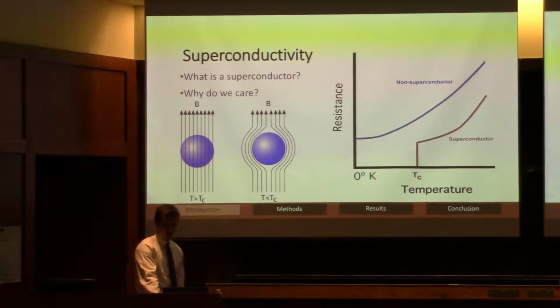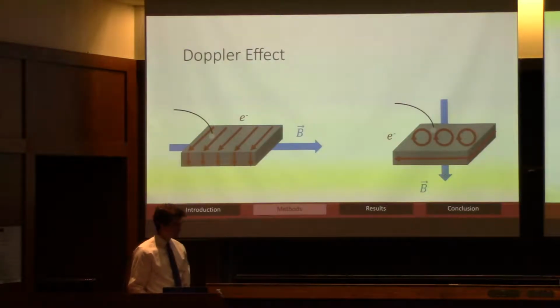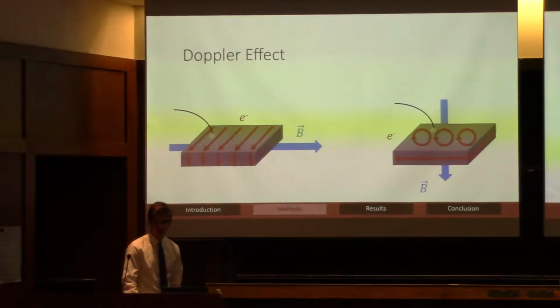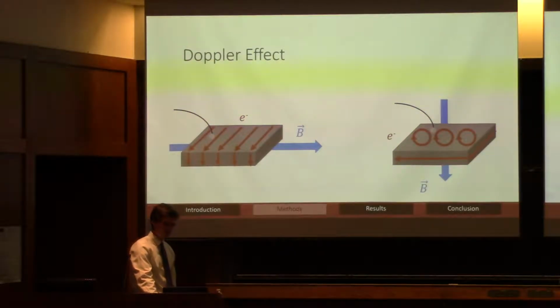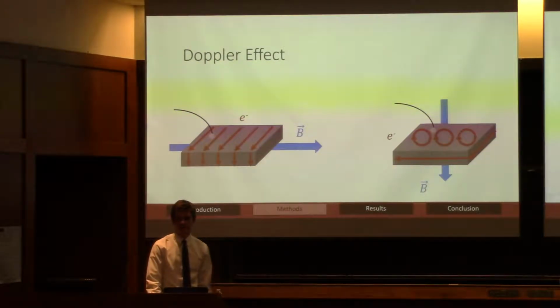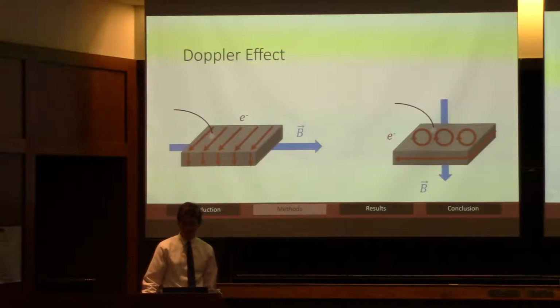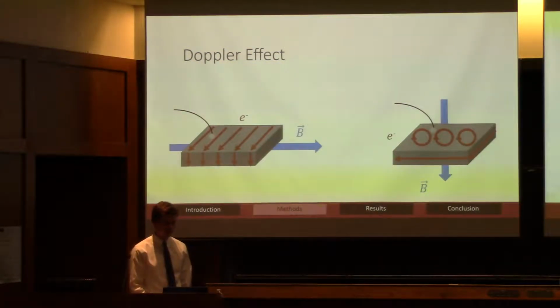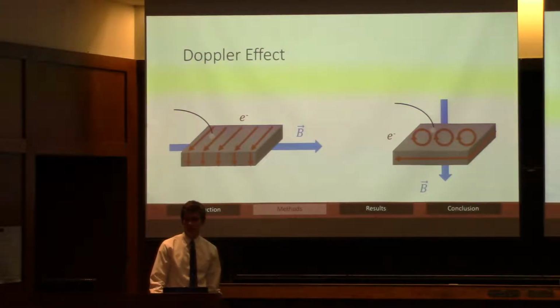Now this Meissner effect leads to something called the Doppler effect. And these are those currents that I was talking about that get induced by that magnetic field. So these are two different orientations of a superconductor in a magnetic field. On the left, you have the face of that sample parallel with the direction of the magnetic field. And these red arrows are the direction of that superconducting condensate that's moving around that sample to cancel out that magnetic field. So as you increase the strength of this magnetic field, you increase the momentum of that condensate.